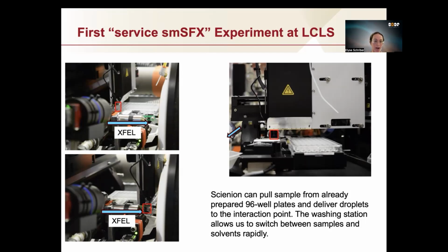So in this case, we have a very small glass nozzle that pulls up sample from the 96-well plate. It then goes and delivers that sample to the interaction point here. And then we were able to collect data for however long we need to. We can screen for 3 minutes.